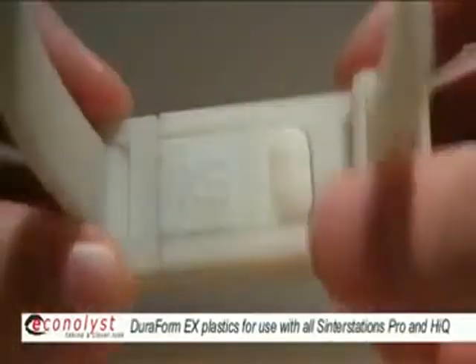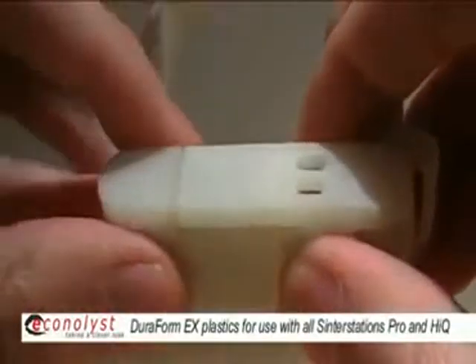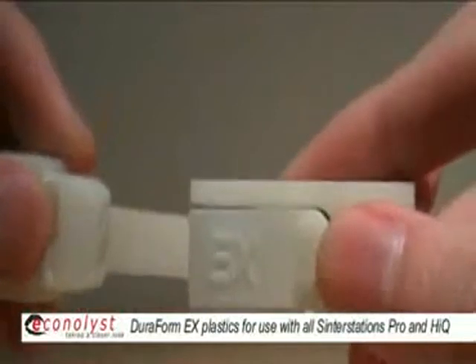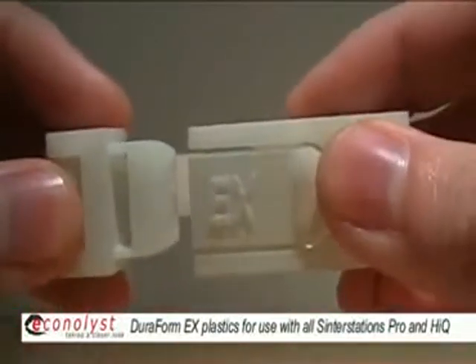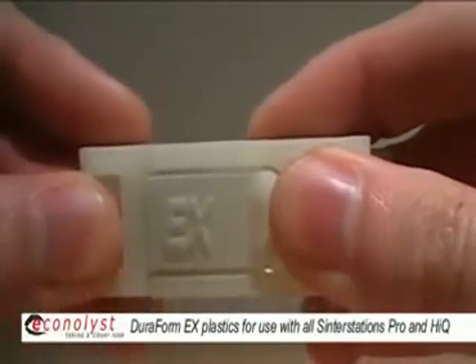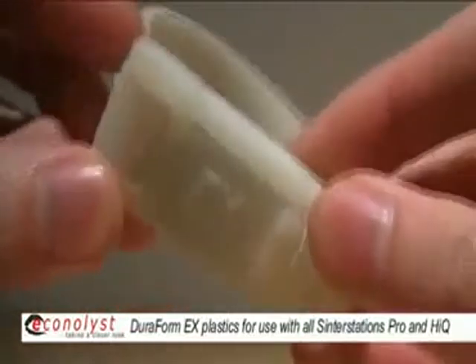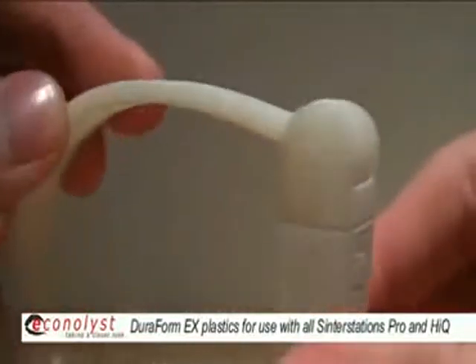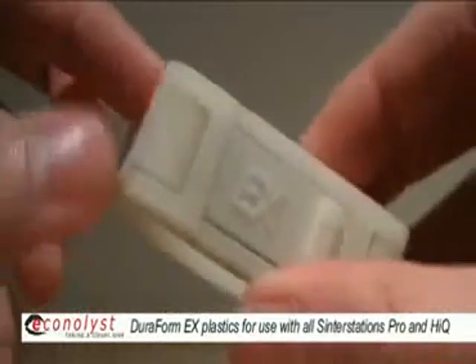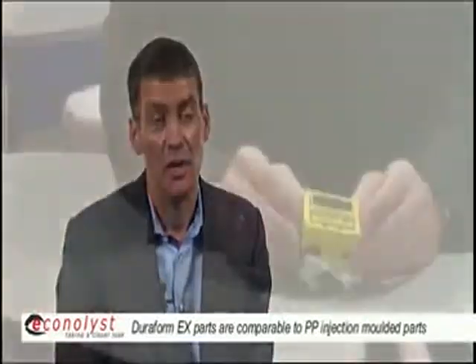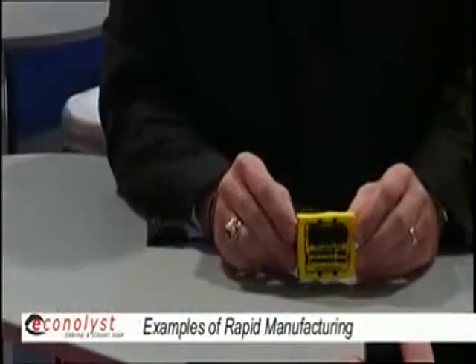We also have a newer material called Duraform EX, which is a next-generation polyamide system, and it has enhanced toughness compared to the earlier generation Duraform systems, and in fact has elongation at failure and unnotched and notched IZOD values, which are actually as good as or exceed molded parts made from polypropylene ABS engineering plastics.